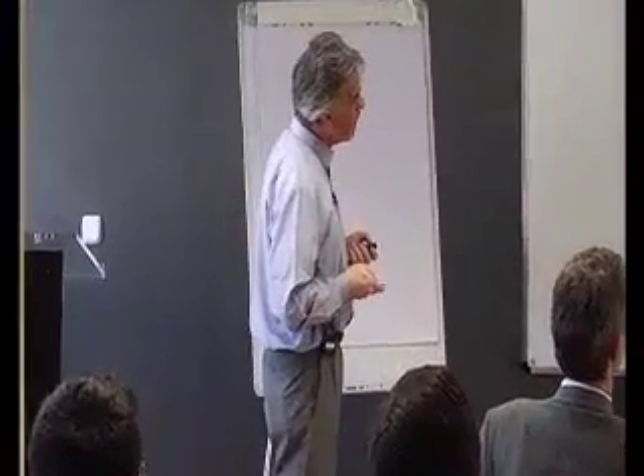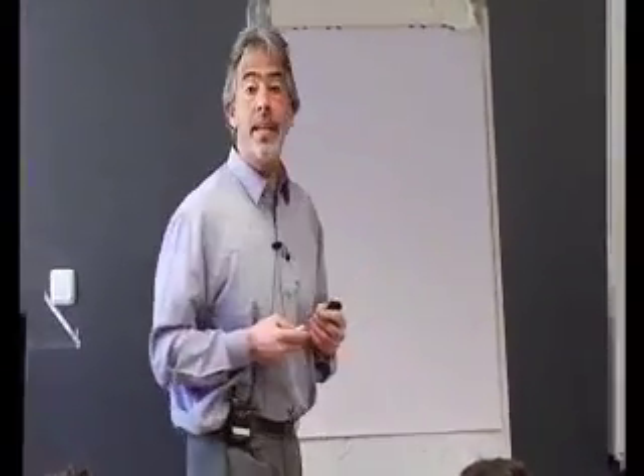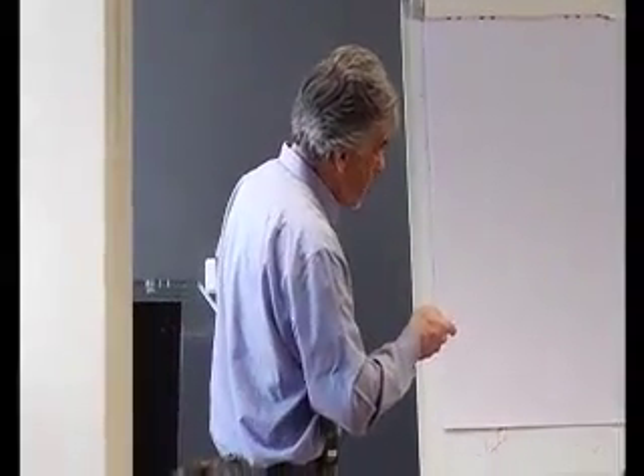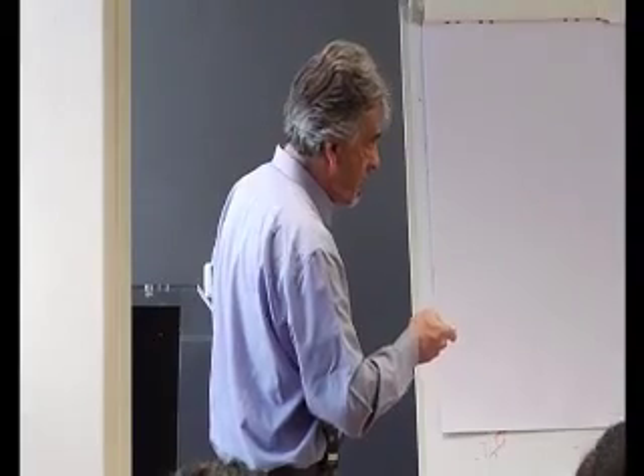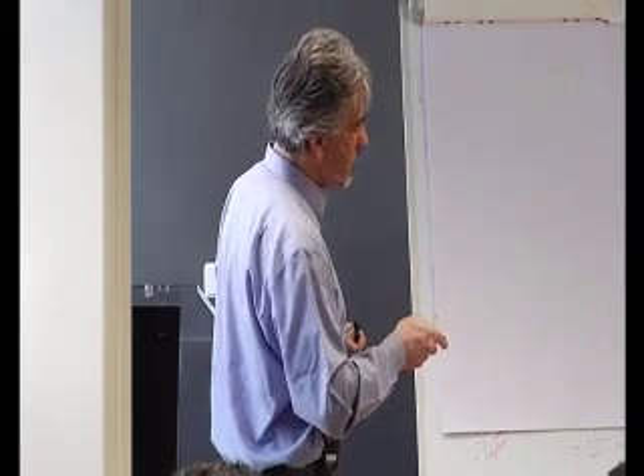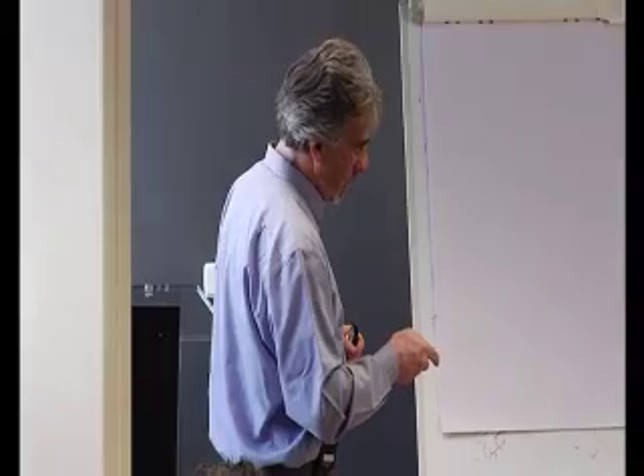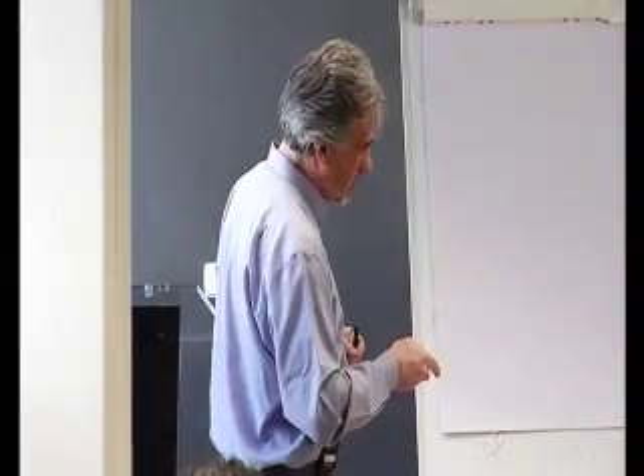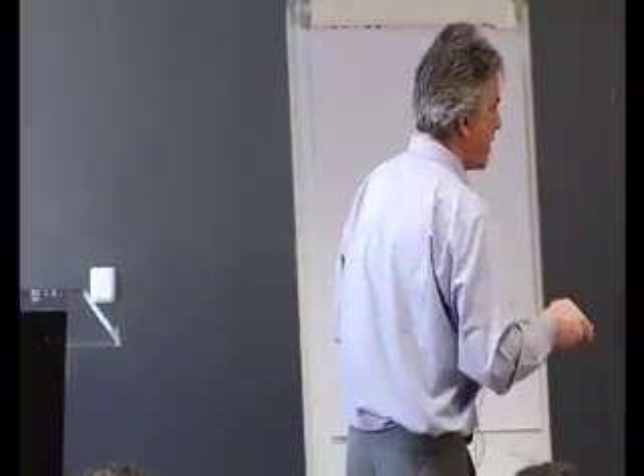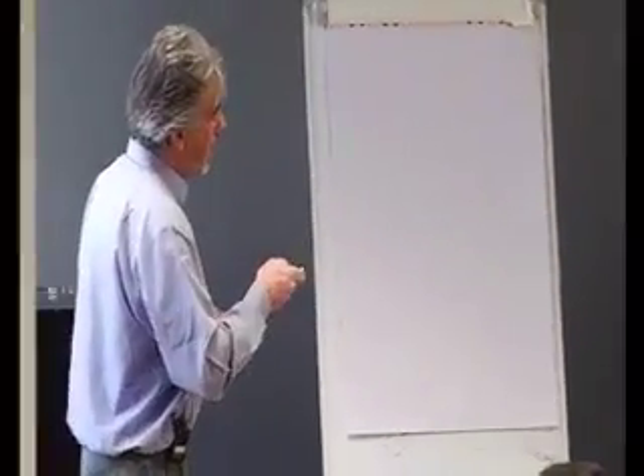But let me show you an example of a non-volatile system, and this is the case of using cerium oxide, ceria. So in the first step, cerium oxide is dissociated. This is a non-stoichiometric cerium oxide with a lower valence, and oxygen is set free. And then in the second step, the reduced ceria is reacted with water and CO2 to produce the syngas. This is a system that we studied in collaboration with Caltech, the California Institute of Technology.